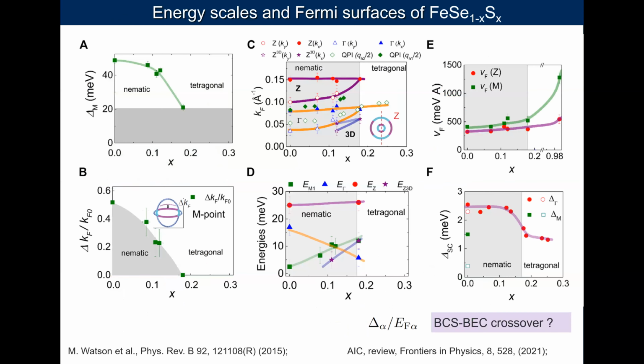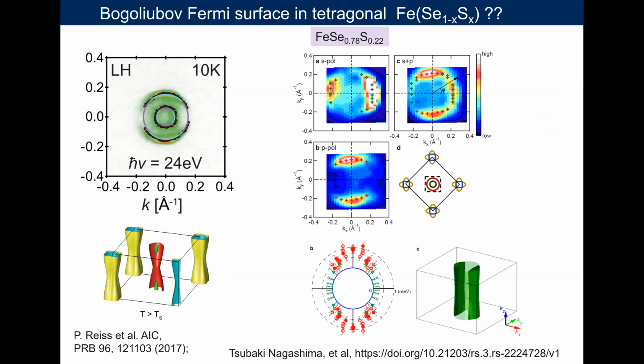Is there any other evidence for broken time reversal symmetry? There are some muSR data suggesting that could be possible, but time reversal symmetry breaking has been suggested to occur everywhere, not only in the tetragonal phase, but also where the nematic phase is. So, this proposal has been for the tetragonal case, so I don't know how that is reconciled with this. Because if time reversal symmetry breaking is everywhere, then we should see these effects in other places, I suppose.